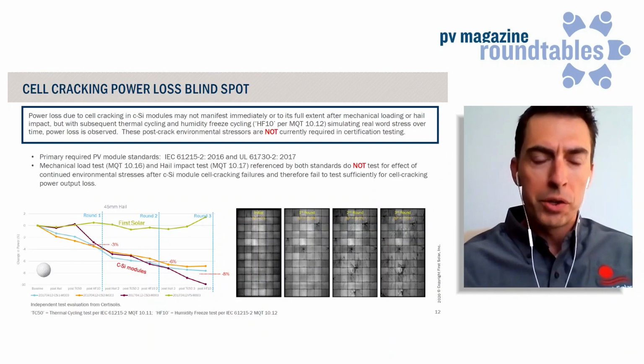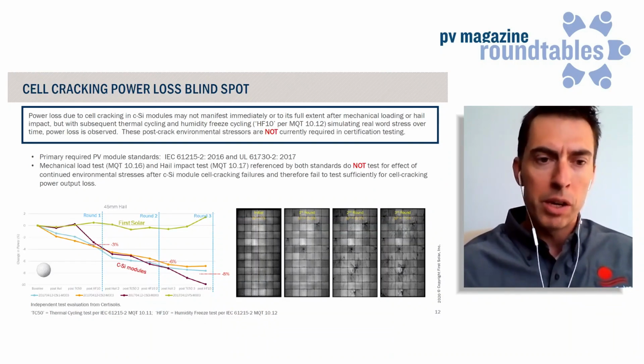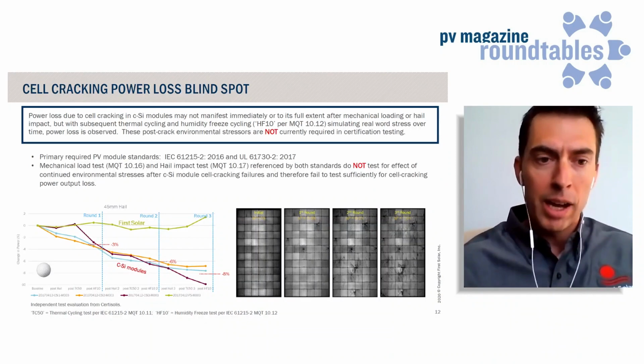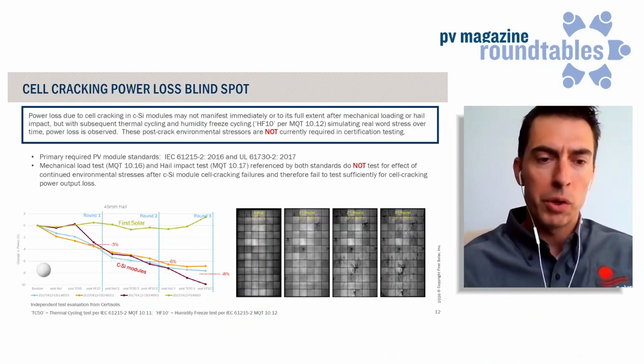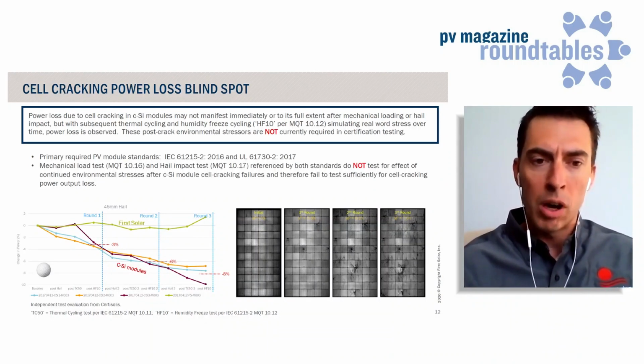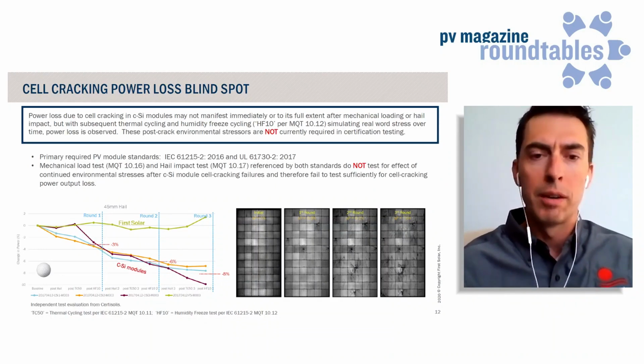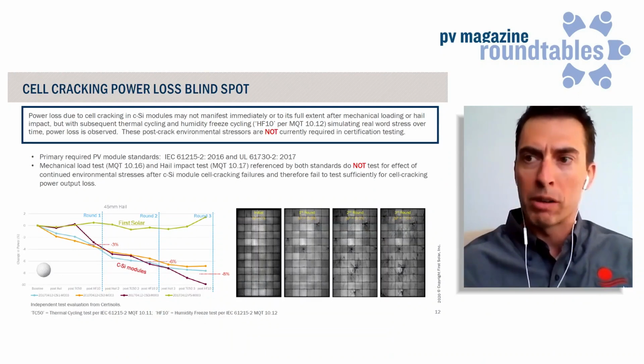The IEC standards that are out there today provide a basic level of evaluation, but they do not apply the thermal stresses that you see here, and so have a blind spot relative to the long-term impact when modules remain exposed after being damaged by a severe weather event or otherwise impacted by microcracks.